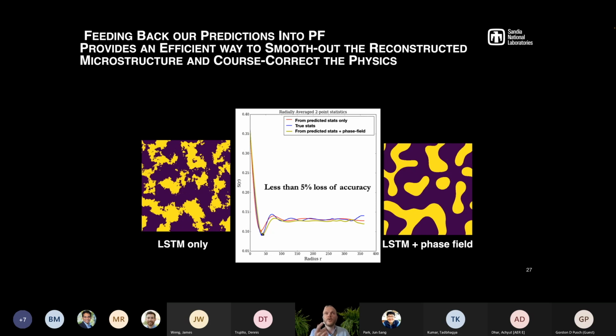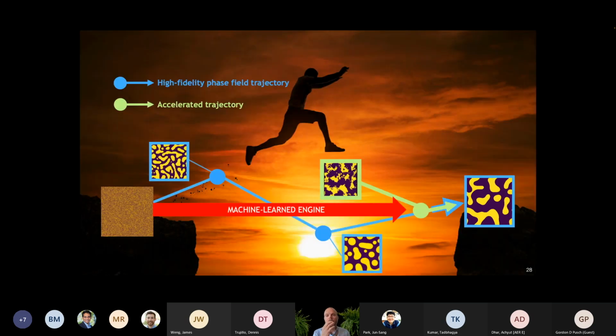Here I'm showing you an example using our first method, where if you just keep running your LSTM architecture and trying to predict evolution over long time scales, the reconstructed microstructure is not so great. However, if you take that microstructure and feed it back into your direct numerical simulation framework, not only do you smooth out the microstructures, but you also improve the accuracy as compared to direct numerical simulation. In a nutshell, the way this leaping in time works is you start with a given microstructure, use your machine learned engine to leap in time, and then go back to direct numerical simulation, bypassing all the very expensive time frames that you would get from direct numerical simulation.